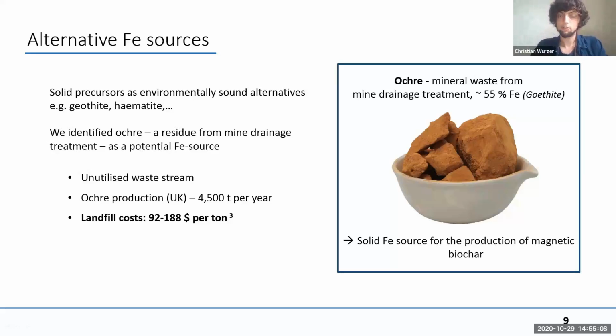That's dry ochre sludge, and if you touch it, it will become powder. So the ochre has around 55% iron content, which is mainly from goethite. And the interesting thing, besides being an unutilized waste stream, is that ochre currently has landfill costs between $90 and $180 per ton. So if you use this material as feedstock, you actually can make your production a lot cheaper.